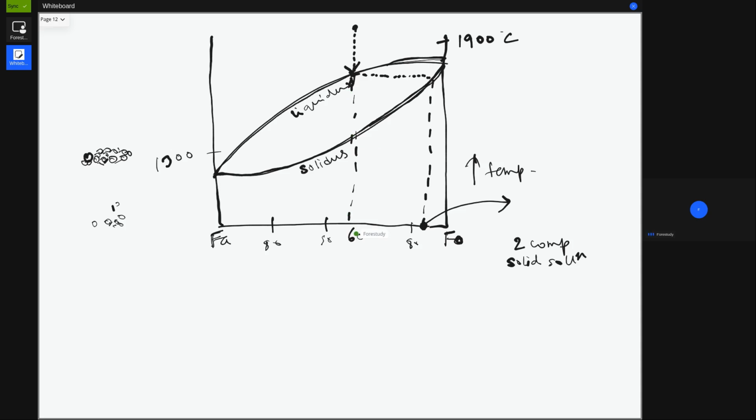But the first mineral that has crystallized here can be identified using this graph: Forsterite 90, Fayalite 10 is the crystal that is being crystallized. The first crystal is of composition Forsterite 90, Fayalite 10, whereas the melt that just hit the liquidus curve is of composition Forsterite 60 and Fayalite 40.